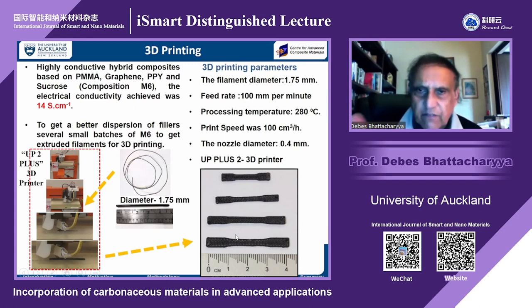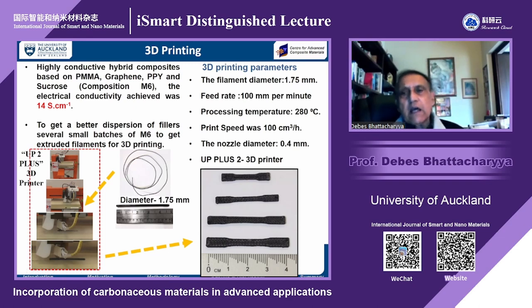So we used a very, very cheap 3D printer now. We are using much more expensive 3D printers, but for student projects and all the time, we did not want to occupy a really good machine. We were trying out on a cheaper machine, but we did it. And our feed rate, you can see, is 100 millimeter per minute, that you can also control. And by controlling that, you can control the quality of the specimen and the properties.